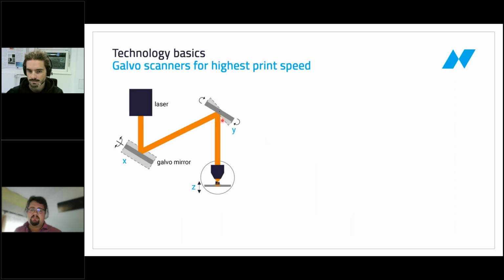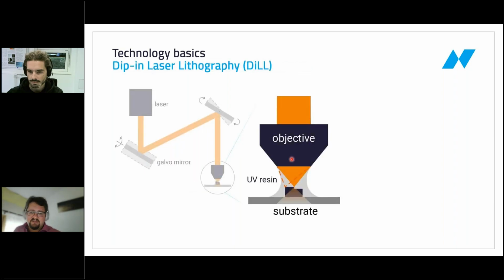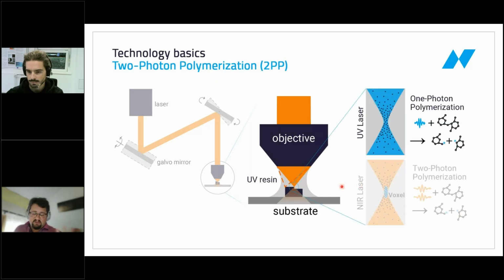But let's dive into the two-photon polymerization part. So also here we have a laser source. The laser beam is moved around by galvo mirrors in this case, and it is focused through a microscope objective into a reservoir, which is mostly just a big drop of UV resin. And then again, you scan layer by layer and you cross-link the UV resin locally. Naively, you would think you would also use a UV laser, and then each individual photon would have enough energy to start a cross-linking reaction, exciting a photoinitiator, and then you could locally polymerize. However, this does not give you the right confinement, especially in the Z direction. You do not get a good confinement here, so you would have a larger region of this double cone, basically cross-linking in every position.